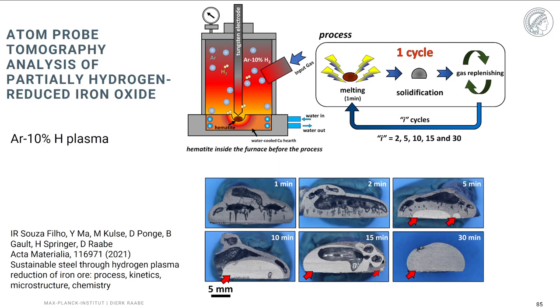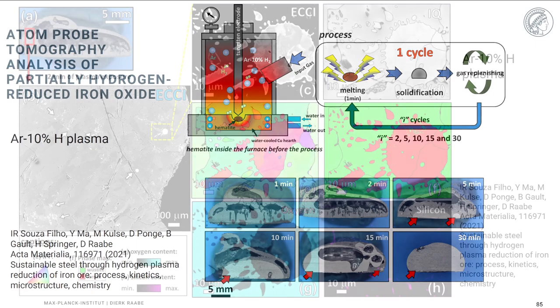And we found that a very interesting and viable alternative to the direct reduction by using hydrogen, because here the efficiency of the consumption of hydrogen is very good. And secondly, also if you go through the direct reduction route, at the end of the process, you must put your iron sponge that comes from the direct reduction anyway into such an electric arc furnace.